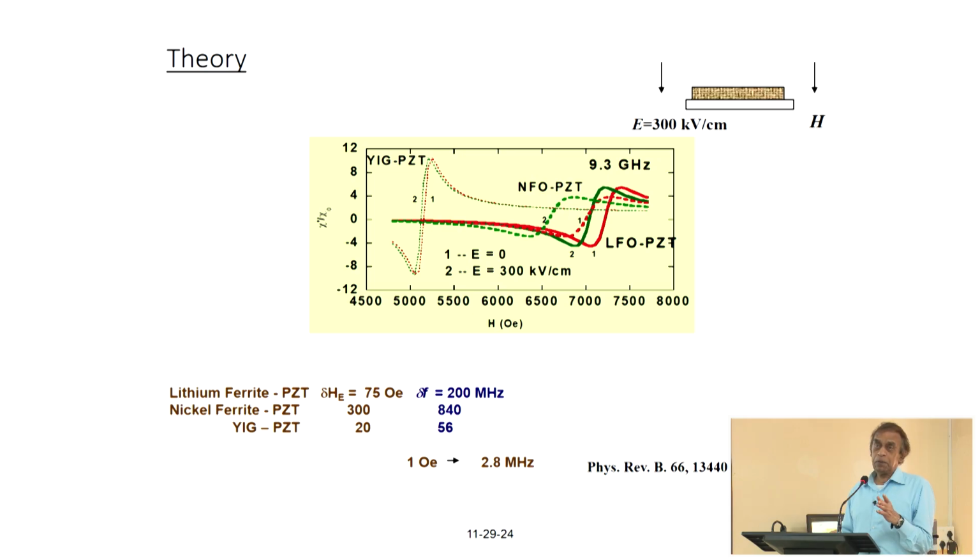So, the tuning in this case is small, but it is good enough if there is a device operating at room temperature and you want to make it operate over a wide change in the temperature, maybe from 0 to 60 degrees. Then the tuning that you can do with the voltage is enough to compensate for any shift in the temperature of the device. So, it is a very limited capability, and we cannot tune the device over several operating bands. That is not going to be possible.